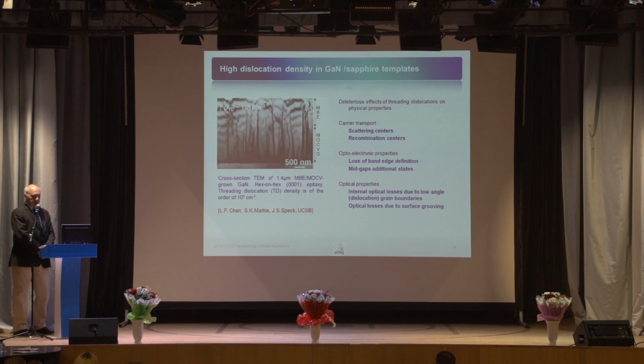These defects are dislocations, so-called threading dislocations, in the typical gallium nitride layer grown with metal organic chemical vapor deposition, or MBE, on the sapphire structure of this gallium nitride layer shown here. And we can see a lot of these dark lines with very high density. The density is 10 to the power 9 per square centimeter, which is extremely high. And these dislocations are very bad for carrier transport, for optoelectronic properties, and for optical properties. Therefore, there is a challenge to reduce the density of these threading dislocations.